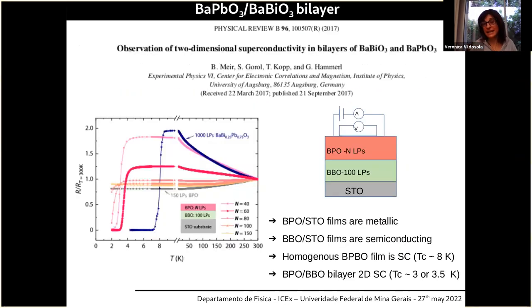But I happened to see a paper in the literature that claimed to observe two-dimensional superconductivity between barium bismuthate and barium lead oxide. I started to be enthusiastic again in this system, because it is not a surface of barium bismuthate, but it is a two-dimensional behavior at an interface. And they managed to build this heterostructure of barium lead oxide, I will call it BPO, on top of BBO and on top of STO.